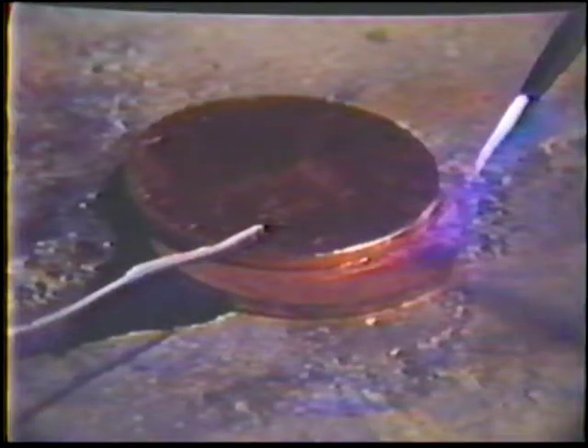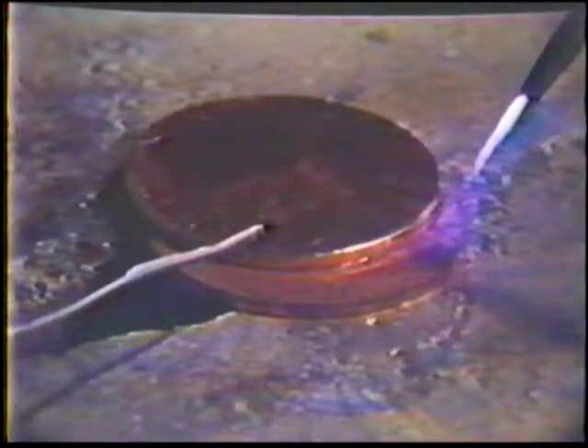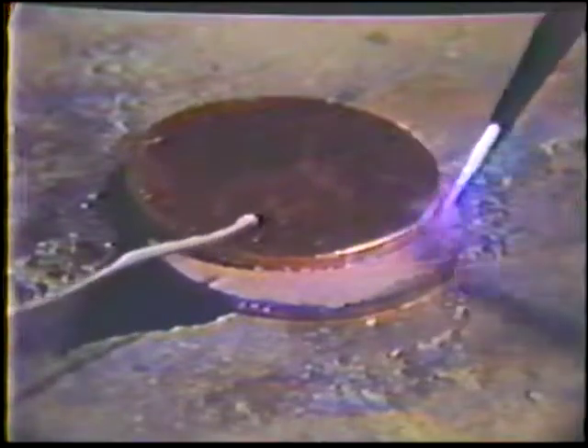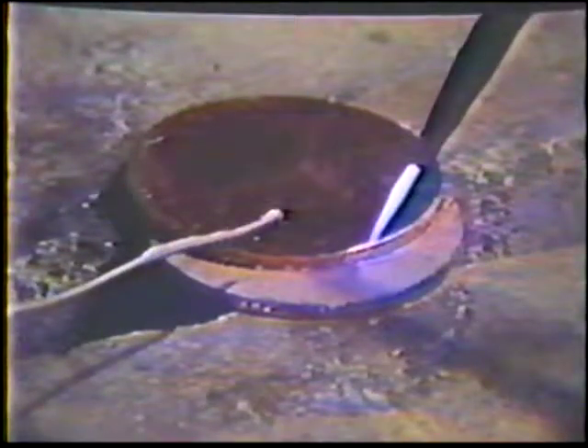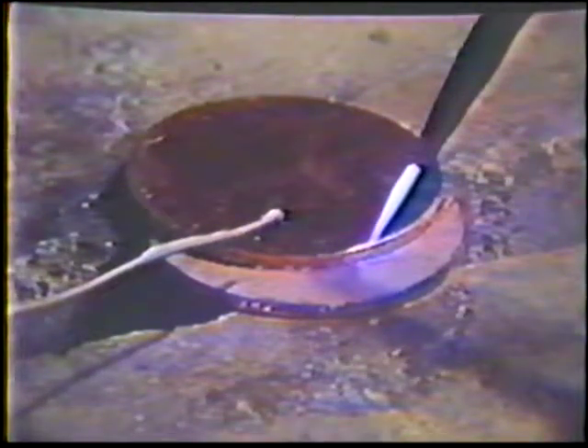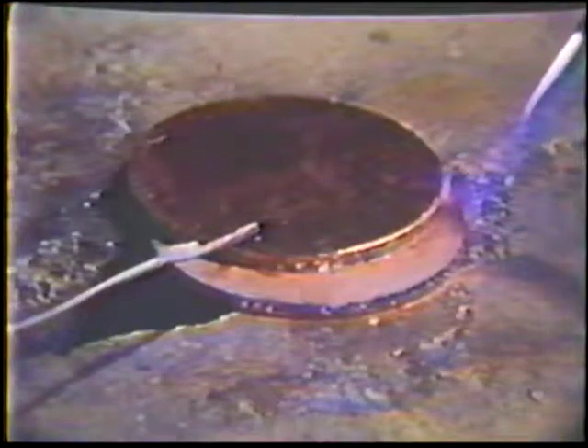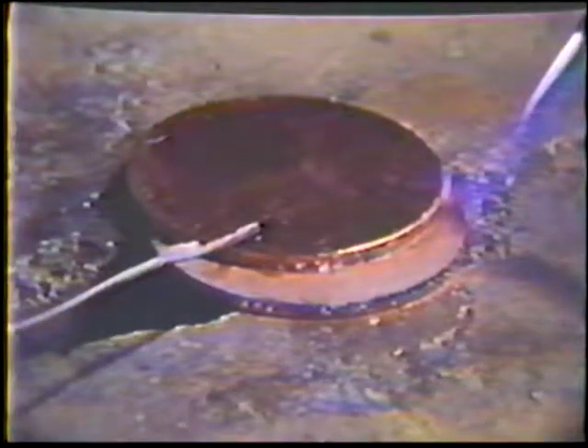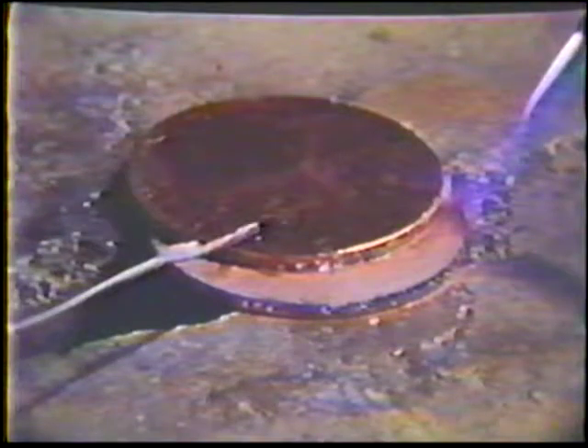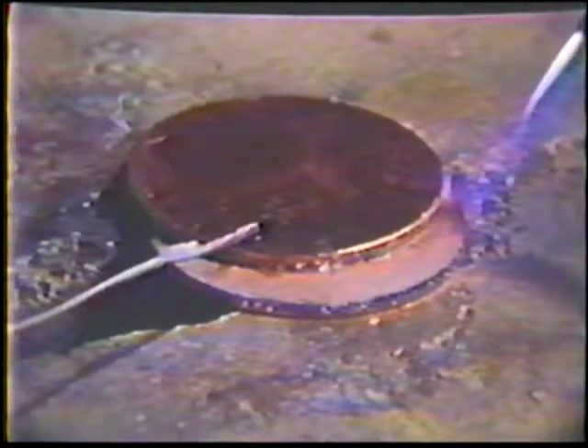Adjust the torch for a slightly carburizing flame, and hold the tip of the feather about 1/8 inch over the lapped area. Move the heat around without pointing the flame directly into the joint until the flux turns into a clear, watery liquid. Then touch the filler metal to the edge of the joint to see if the metal is hot enough to melt it. If not, continue applying the flame evenly to the area for a few moments and try again.